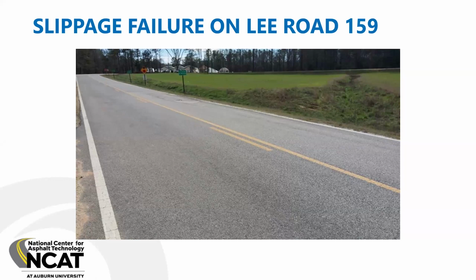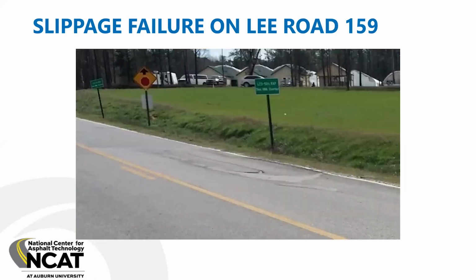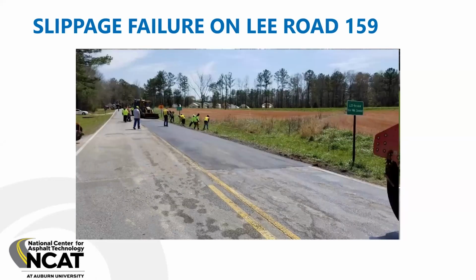And because this happened, it grew, it got bigger. We came in and did a repair with a BMD designed thin lay to have a little less mixed stiffness, and the replacement is still in service to this day and performing really well.